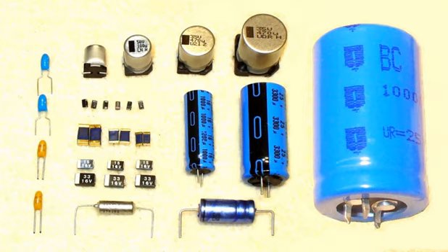For antique radio equipment or for electrolytics built in the 1970s or earlier, preconditioning may be appropriate. For this purpose, the rated voltage is applied to the capacitor via a series resistance of approximately 1 kΩ for 1 hour. Applying a voltage via a safety resistor repairs the oxide layer by self-healing. Capacitors that fail leakage current requirements after preconditioning may have experienced mechanical damage. Electrolytic capacitors with solid electrolytes don't have precondition requirements.